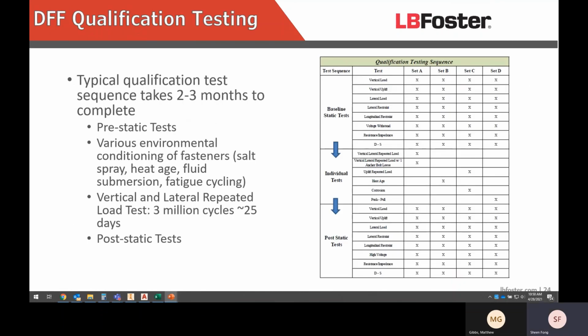Once a fastener has been developed, we will make the part and run it through the qualification testing. Typical qualification test will take about 2 to 3 months to complete. This table to the right is just a generic qualification test that we will perform to certain agency specifications. They always comprise of a pre-static sequence of tests, which will contain the vertical load, vertical uplift, lateral loads, longitudinal, electricals, and dynamic to static test.